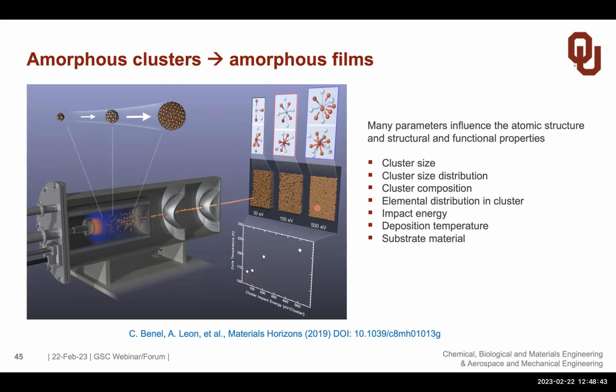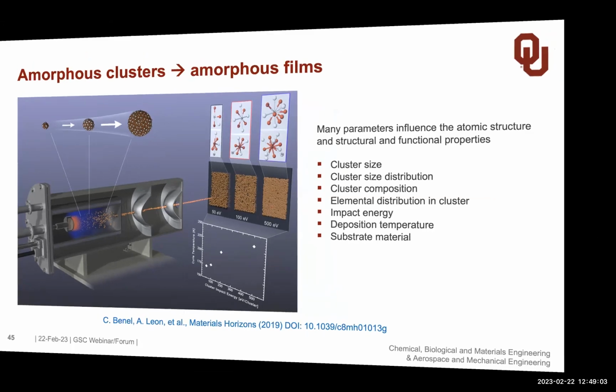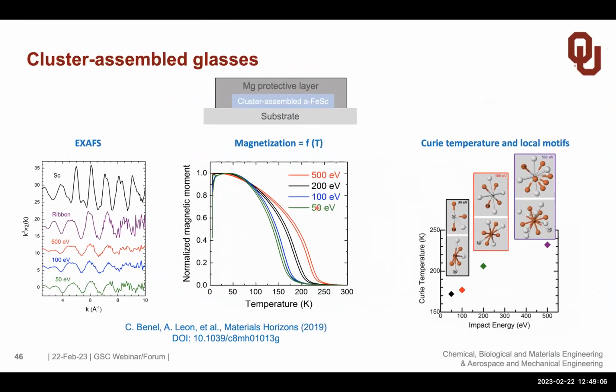So imagine you take a snowball and you throw it hard against the floor, it smashes. So it's like rapid quenching. If you let the snowball fall softly, it maintains its structure. And this would be building up an amorphous structure from small particles which maintain the original nature of the particle. And we have done that here. We show the magnetization curves, and you see clearly the shift of the Curie temperature in this material.